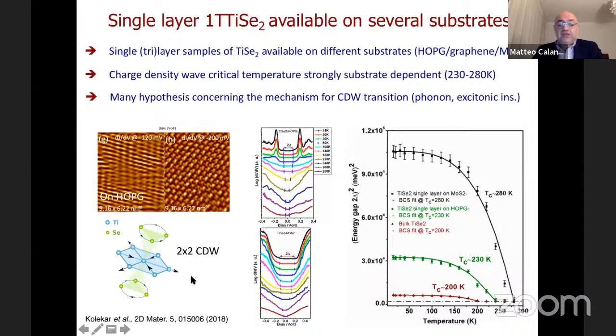And it's actually a very beautiful pattern for a charge density wave, in which you can see the titanium atoms are the blue ones, and the central titanium stays where it is, while 3 titanium goes close to the center, and 3 titanium moves away from the center. Sorry, not selenium, titanium, I repeat. So there is a fixed titanium in the center, 3 titanium move close to the center, 3 titanium move away from the center, and the selenium on top and below, they turn in such a way